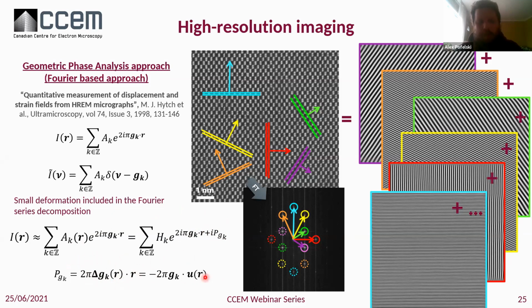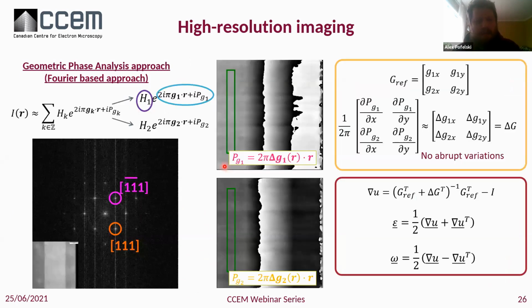So it's possible to transform it to have, if you prefer, U, which is the displacement field here. So then the idea would be to say, okay, let's isolate, for example, different lattice families to try to extract just this phase component, and see if we can see the variation of them. So this can be done by taking a Gaussian mask in Fourier space along one reflection, and then this isolated frequency comes back into real space.